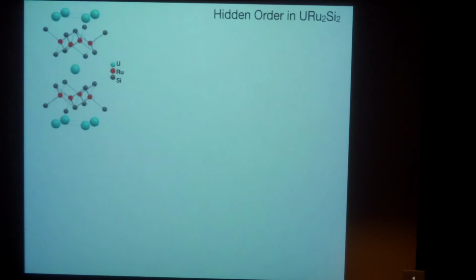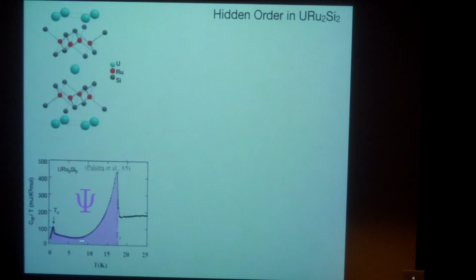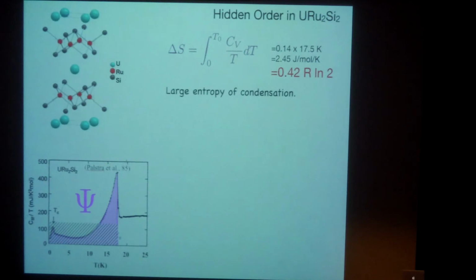But here is the material. It has the same structure as the 122 iron-based superconductors. In fact, the ruthenium replaces the iron and the uranium are here. And if you measure the specific heat capacity, you see a whopping great big anomaly. There's a huge amount of entropy there, about 1/3 R log 2, except no one's been able to detect the order parameter. They used to think it was magnetism, then they found the moment was very, very tiny, and then they found the moment ceased to exist when they made the samples very pure. Well, a large amount of entropy, if you do the math, but no order parameter detected.